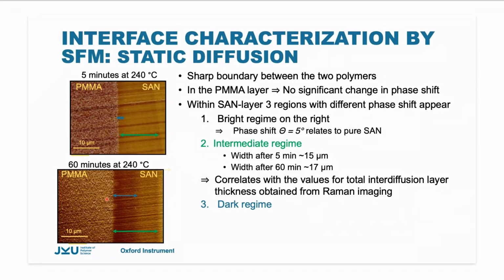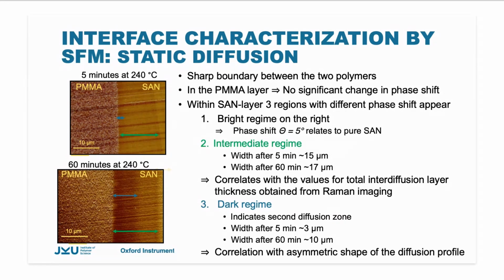And then we have a third dark regime. This indicates a second diffusion zone. The width is after 5 minutes 3 micron and after 60 minutes 10 microns, and this is in good accordance to the asymmetric shape of the diffusion profile. But it's still not clear what is going on the molecular scale. Here further investigations will be necessary.